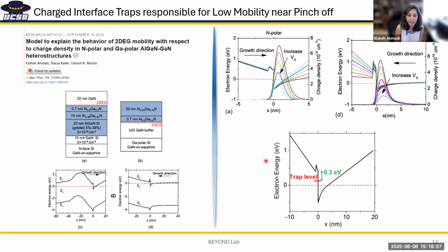Now, keep this in mind. When I was doing my PhD, we came up, just by simulations, with a proposal that there are shallow trap levels at that interface where the two-dimensional electron gas forms, which can really affect the mobility. And in nitrogen polar, as we are applying a negative gate bias, we are pushing the wave function closer to the interface, and then the mobility drops because of basically ionized impurity scattering. It's not impurity, these are traps, but still they are charged traps, and so they can significantly reduce the mobility.